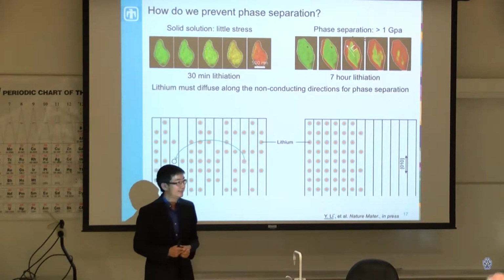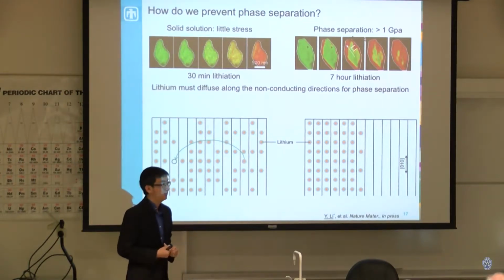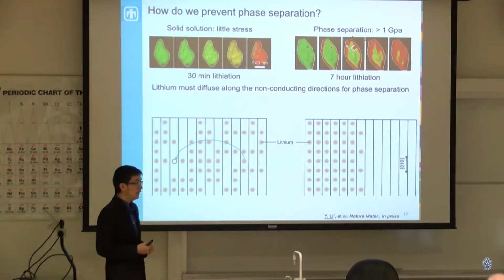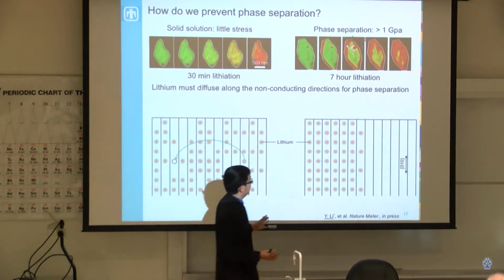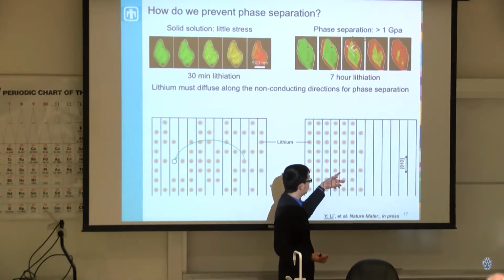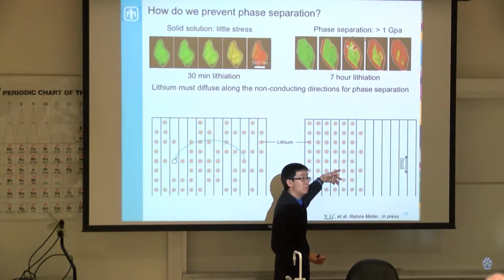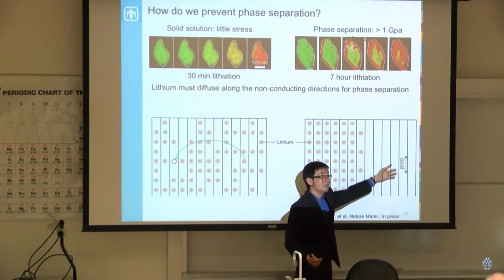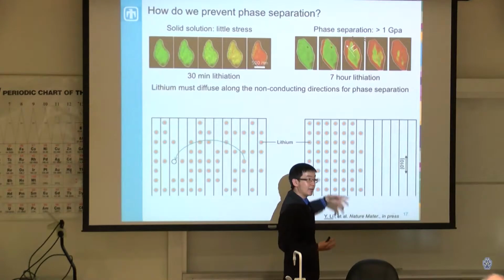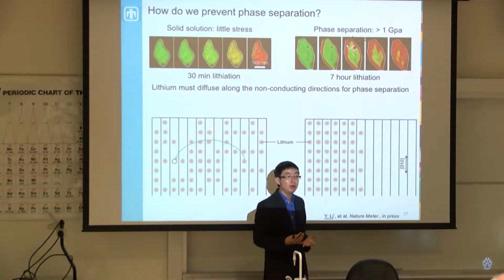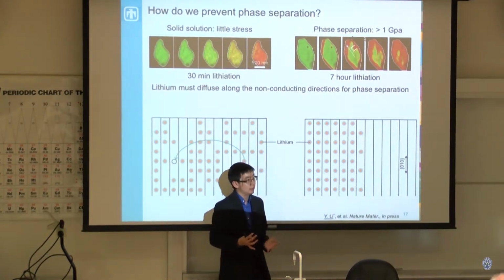I guess if I could follow up, so that's the mechanism, but the negative result for use in batteries when you're having this separation is? Yes, that is an increase in the mechanical stress of the battery. The reason you get a higher mechanical stress is because this part of your lattice is bigger than this part of your lattice. So one part is compressively straining the other part, while the other part is tensilely stressing it.